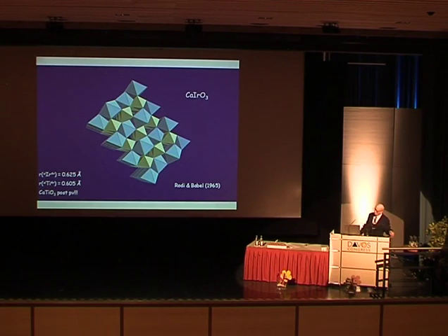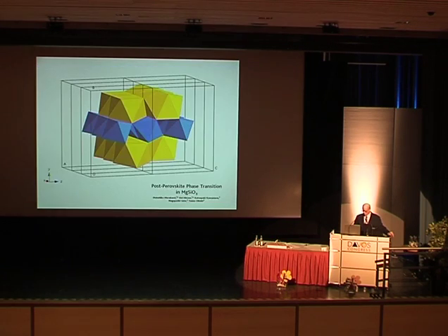And if you look at that diagram I showed previously with the plotting of the radii of A versus A over B, you can see that the calcium iridium oxide falls right over perovskite itself, calcium titanate perovskite. So it's amazing that no one looked at it and thought about it as a possible high-pressure mineral phase.